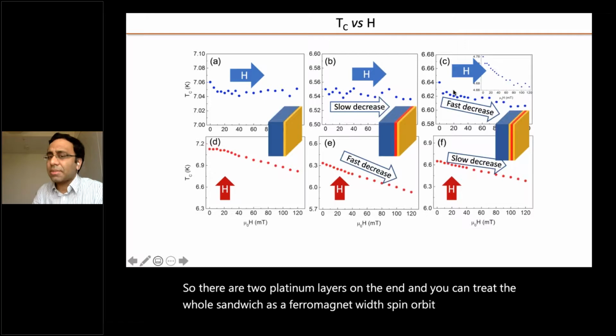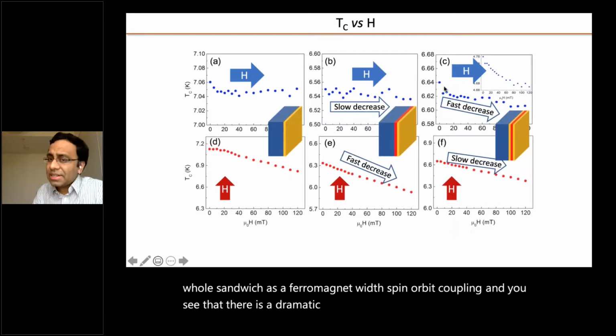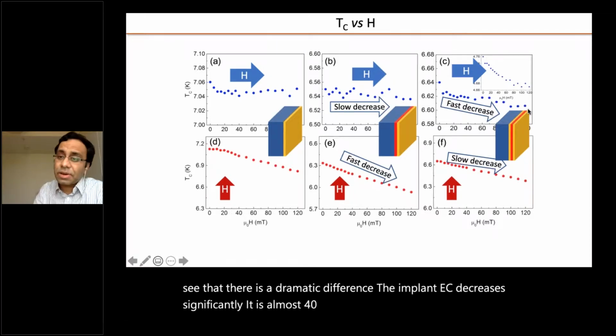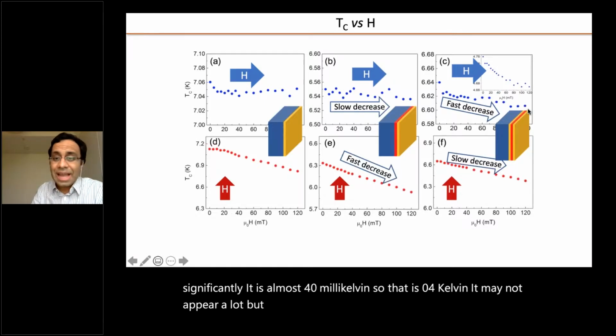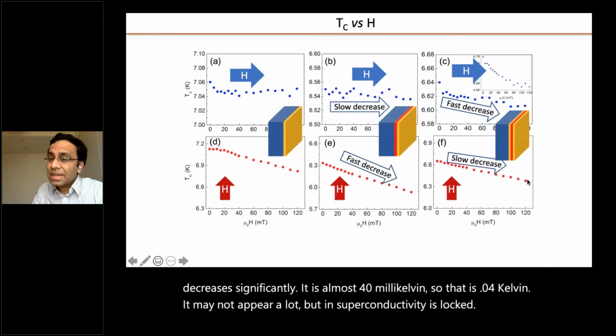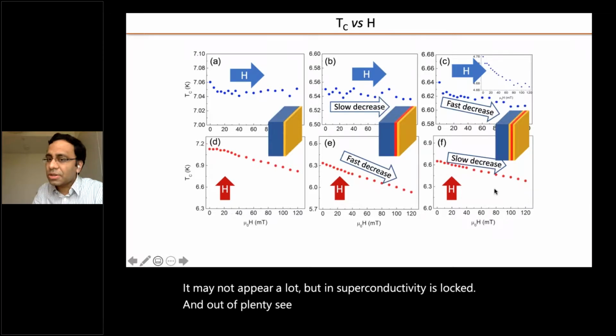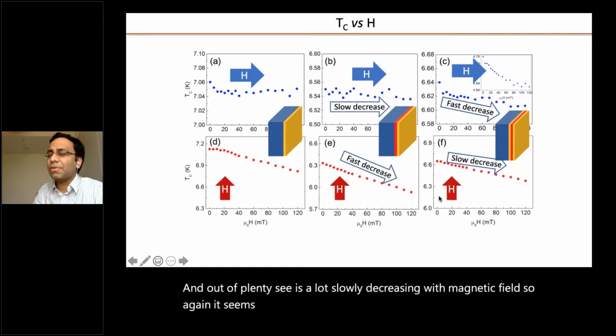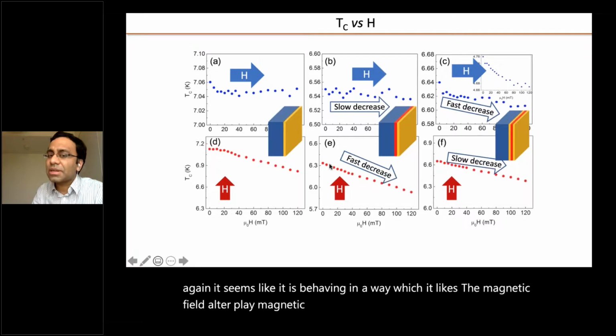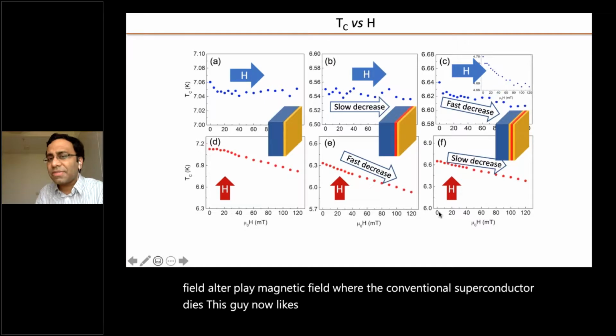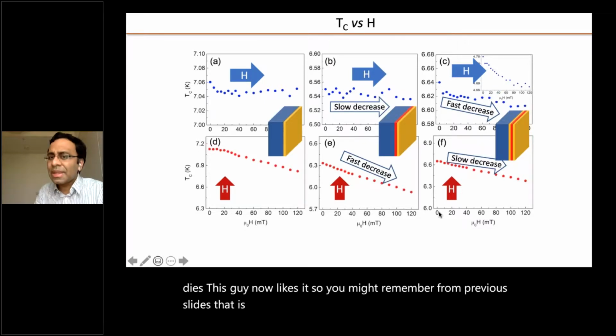And you see that there is a dramatic difference. The in-plane TC decreases significantly. It is almost 40 millikelvin, so that is 0.04 Kelvin. It may not appear a lot, but in superconductivity it is a lot. And the out-of-plane TC is slowly decreasing with magnetic field. So again, it seems like it is behaving in a way which it likes the out-of-plane magnetic field. Where the conventional superconductor dies, this guy now likes it. So you might remember from previous slides that is a signature of triplets.